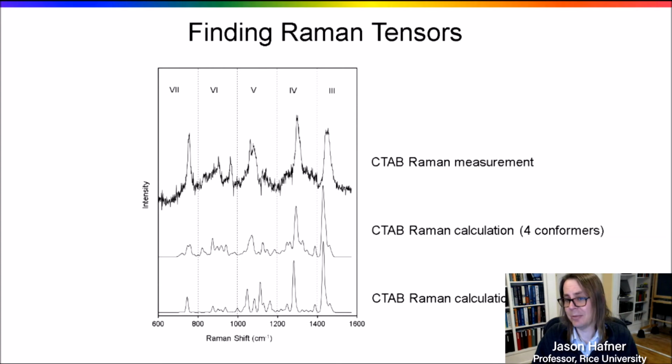That peak is covered, that peak is there, that peak is there. This region looks kind of similar. But we're getting even more realistic, as they don't have straight chains. They have flexible chains, so they're called conformers. Every single bond can rotate, right? So we do a bunch of conformers and average them, and it gets even more realistic because that's actually what's happening in solution. That matches, that matches. We've now sort of built this match better than it was by looking at conformers. And the head group actually got messed up a little bit for complicated reasons.